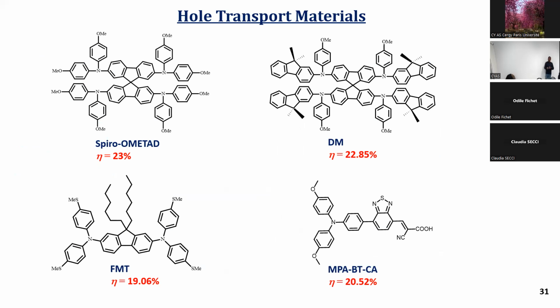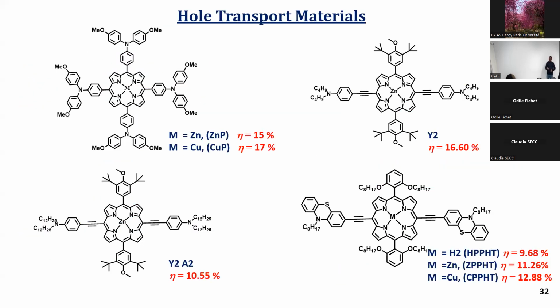Spiro-OMeTAD-based spiro molecules using fluorine have been reported, reaching 22% efficiency. After that, small molecules were taken as hole transport materials and reached efficiency of around 16%. Small molecules are also trying to replace spiro-OMeTAD. In DSSCs and perovskite solar cells, porphyrin molecules were also introduced, and they reached 15% efficiency as hole transport materials.